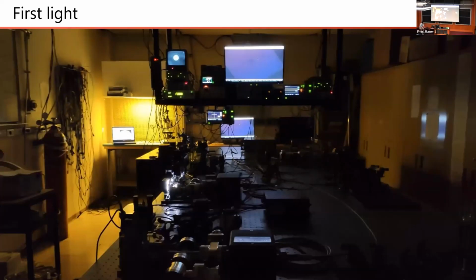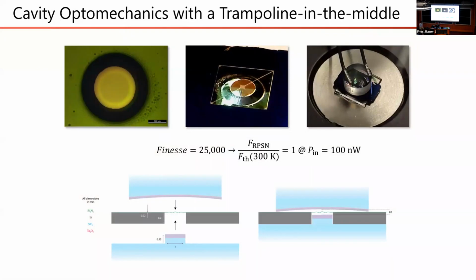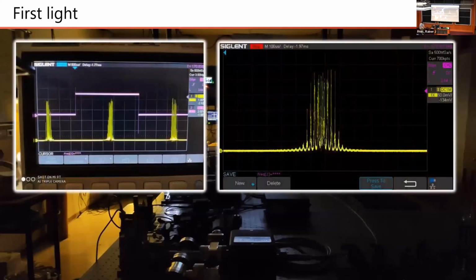So if we take these trampoline resonators and put them in an optical cavity, then we think we can actually reach the radiation pressure shot noise limiting regime at room temperature with hundreds of nanowatts of optical power, which turns out to be really hard. And the reason for that is something we didn't really anticipate at all. The thermal motion of these little nanomechanical resonators can be made much, much, much larger than the line width of the cavity. So we're actually in a regime, something called the thermal intermodulation regime, where the Brownian motion of this little trampoline is much larger than the line width of our optical cavity. And so we actually have to cool our mechanical resonator into the cavity, if you will, in order to even start experiments. So we've been working hard on that.